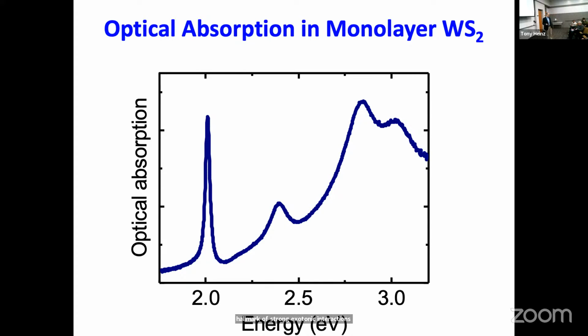But then the next question everybody would ask is, well, how high is the exciton binding energy? And the interesting thing is what you'd normally do is compare the position of this peak with the onset of the continuum absorptions. You'd get excitonic peaks and you'd get band-to-band transitions. But as you keep increasing the correlation effects, the excitonic effects, you kind of lose the band-to-band transitions. So you don't really know what to compare this with.